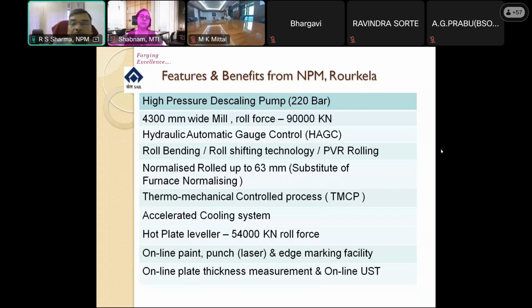In the next slides, I will talk about the thickness variations which the mill can provide. Then this mill has 3 technologies which control the plate shape: roll bending, roll shifting, and PVR. I will discuss this in detail. Then we are rolling plates with normalized rolling up to 63 mm. Since NPM does not have a furnace normalizing facility, with limited facility available in SPP with limited dimensions, what we are doing is rolling with normalized rolling, which is accepted as per standard, and customers are also accepting. So this has helped us in servicing normalized plate up to 63 mm.